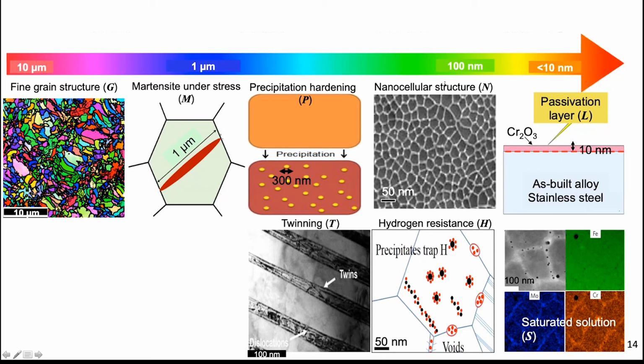Precipitation hardening. When I print a material and when I age it, I produce these tiny precipitates, particles that are usually in the range of hundreds of nanometers. So that is about 1,000th of a hair size. And they impart strength. And twins as well give me strength, but massive ductility. Twins are defects that appear in the material upon 3D printing them.